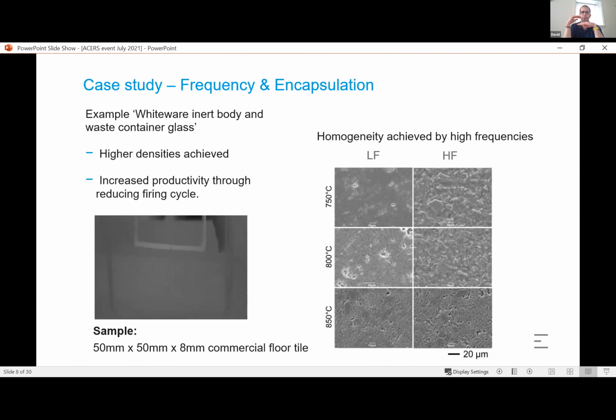But as we start to play with the frequencies that we can use as one of the electric field variables, we start to be able to get more energy into the sample without it localizing. And we can start to not only encapsulate all of those inert particles by igniting that liquid phase, but we can actually start to interact with and melt those inert particles as well. And we get a different microstructure, which is very interesting. In comparison between high frequency and low frequency, there would be some effects in terms of the performance of the material, but not necessarily relevant to a traditional tileware body, as we're talking about here.